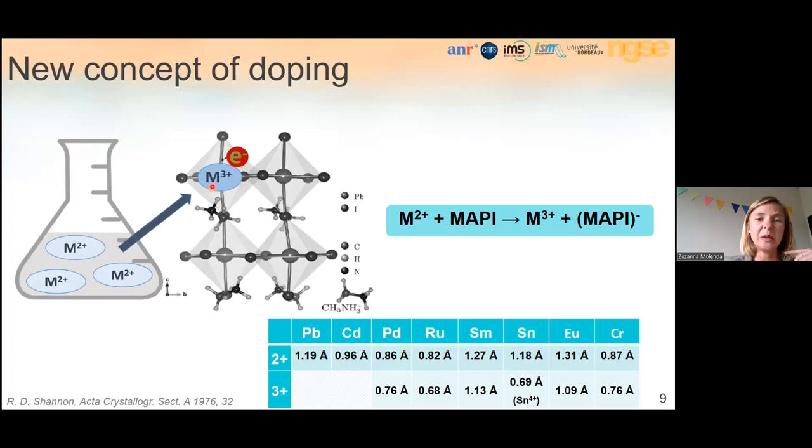Other key properties such as band gap were measured from UV-Vis spectra and are typical for MAPbI₃, unchanged upon doping. Photoluminescence occurs at 780 nm, also typical for MAPbI₃, and we observe complete quenching of the photoluminescence signal for all doping concentrations discussed so far.